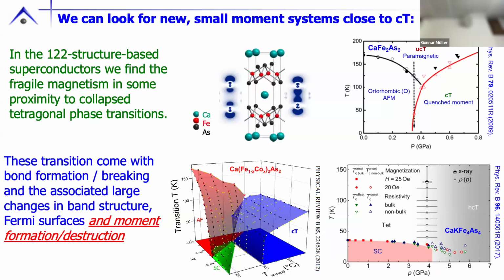And all of a sudden, they bond. So this is basically tuning, in the solid state, a bonding and anti-bonding of these pairs of atoms, or these planes. Yes, Paul? Was that hydrostatic or uniaxial, with different directions of the pressure? This is hydrostatic. When we FIB a little column and then apply pressure, that's uniaxial. You can appreciate uniaxial is more efficient. Yeah. Someone else had a question.